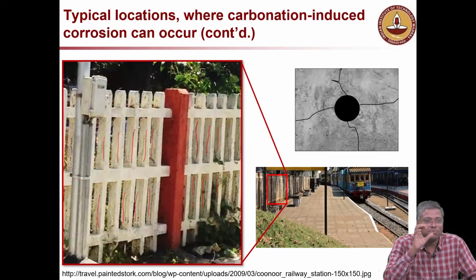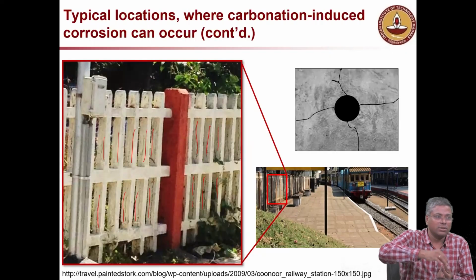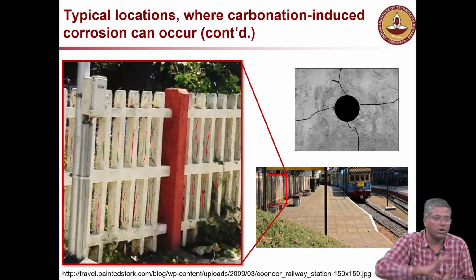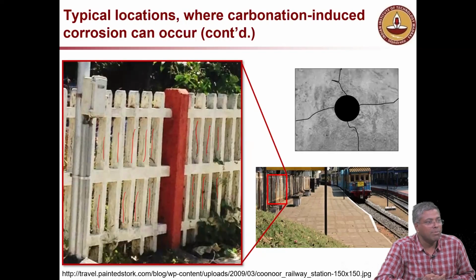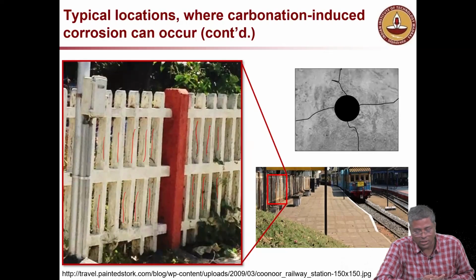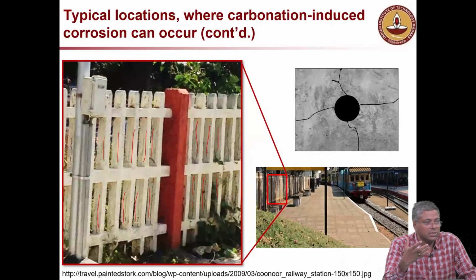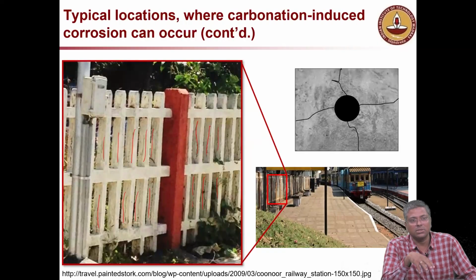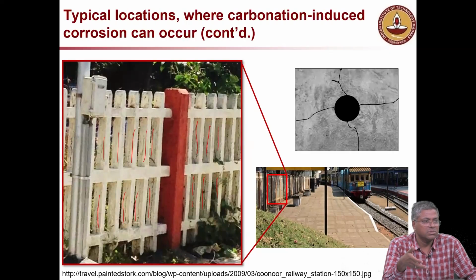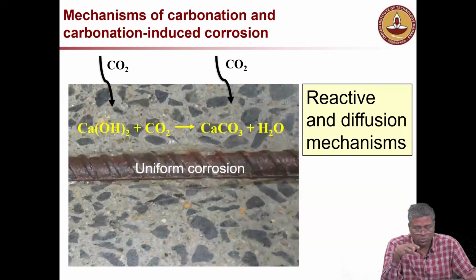This is just mortar with a rebar, one very thin 6 mm diameter rod inside. It is a very good example of carbonation-induced corrosion. It has nothing to do with chloride, and this is something we should not practice if we want longer life. Again, you might say this is not a major structural element, but it is creating waste, which we have to manage later. So what is carbonation?